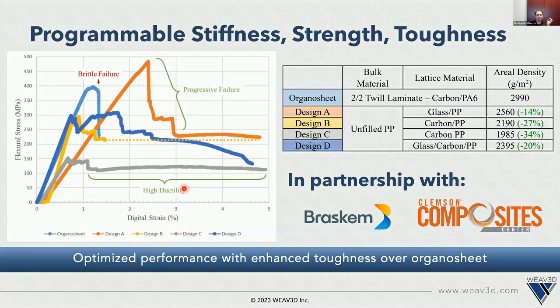But even with just this data set, we were able to show that by tuning the types of materials that you use and how much you use in which areas, you actually can change that stress strain curve pretty much any way you want it. So you'll see this orange one here is a glass design. It's actually stronger than the carbon fiber design, but it's less stiff. Whereas the one that we actually ended up settling on was this design D, this dark blue line.